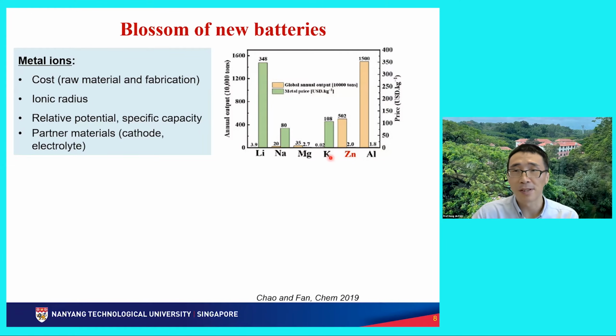If you look at the periodic table, these materials have different ionic radii, right? And we will not just look at ionic radius. We look at the radius of ions, not just the atoms, right? So, for example, the aluminum atom is bigger than lithium, but the ion is much smaller. And also the relative potentials, specific capacities of the metals, as well as the electrolyte material. If you put these materials in the batteries, you have to consider suitable cathode and anode material. So you also have to make sure that you can find partners that can work very well with them.